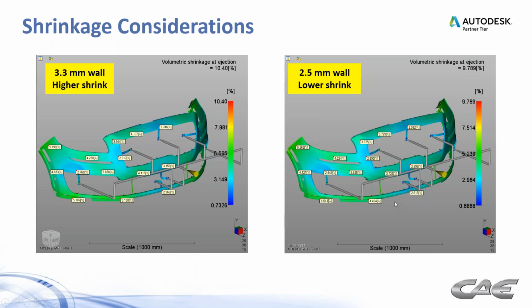So what may be stated on a material data sheet for shrinkage may not apply when you change this part design. Those data sheet numbers are generated under very controlled conditions, and you have your test plaques at a certain wall thickness, and those shrinkage numbers are generated from that. So this matters when you start changing the part design, especially the thickness. Your shrinkages change, and then your assumptions about what you cut into the steel need to change along with that.